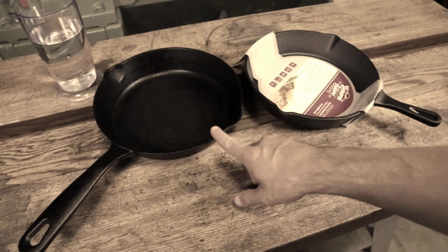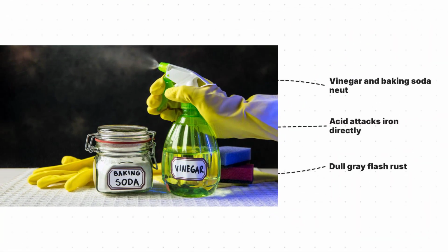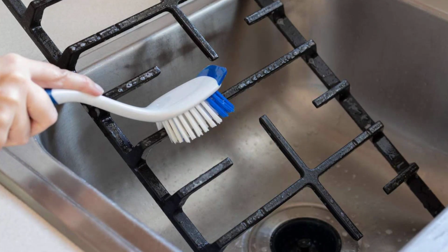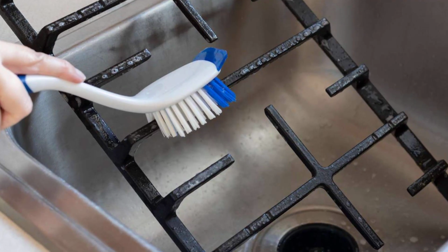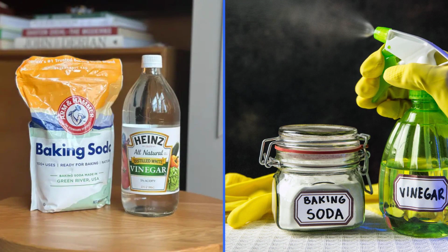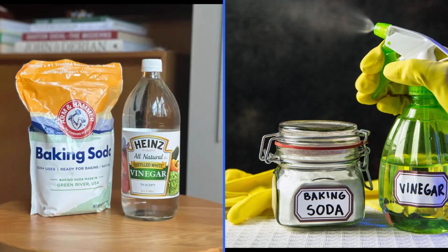Vinegar, on its own or mixed with baking soda. Mixed together, they react and neutralize each other, and what you are left with is mostly salty water with the useful properties of both gone. Vinegar alone is an acid, and acid does not break down a polymer film either. What acid does do is attack iron directly, which is why a vinegar-soaked cast iron grate often comes out looking dull gray and flash rusts as it dries.